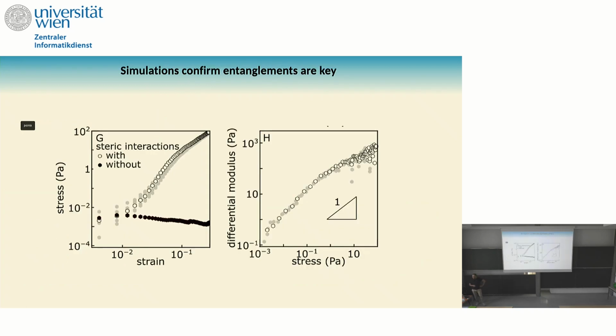Okay, can we prove that the mechanism behind the stiffening in that network is coming from the contacts? And the answer is yes. So you can do pretty much whatever you want in simulation. One thing that you can do is to make a simulation where you apply this deformation and measure the stress as a function of the strain, with steric interaction, in the sense that if you have two filaments that try to cross each other, they cannot. But then you can turn off this steric interaction.